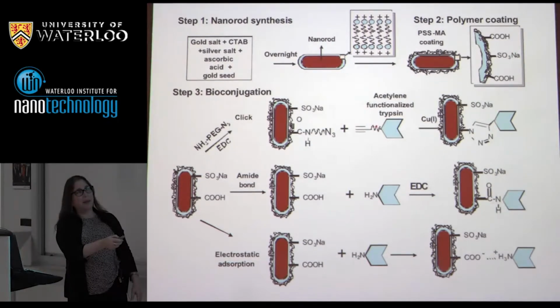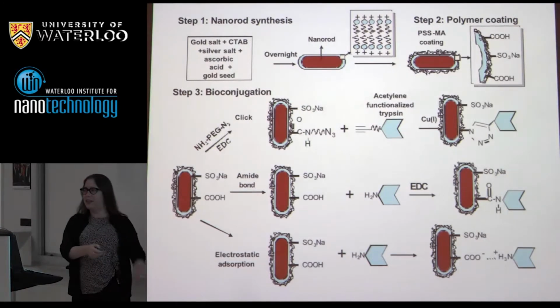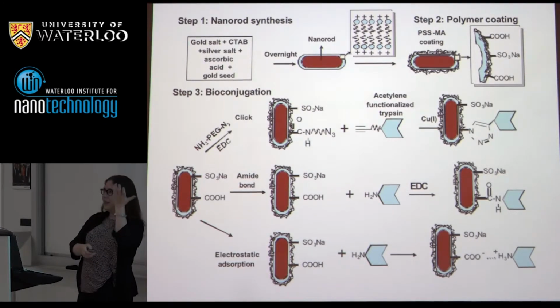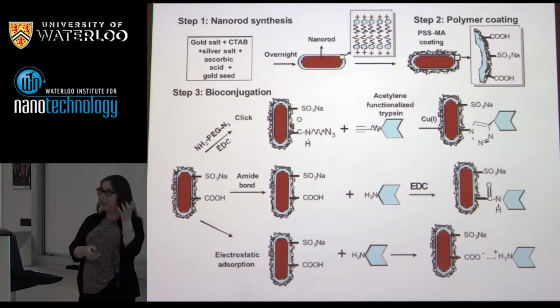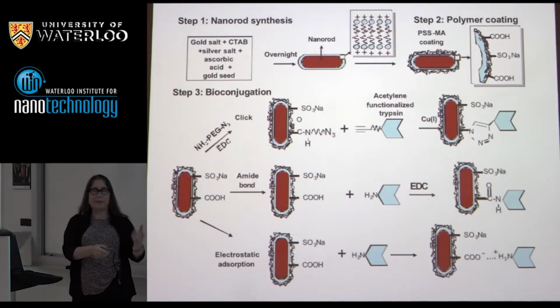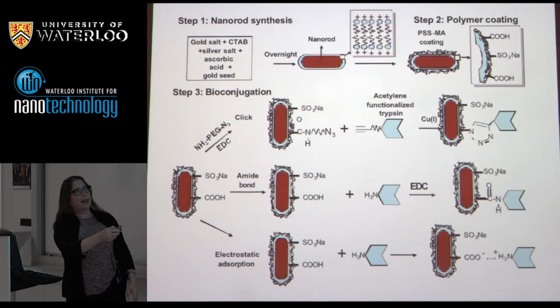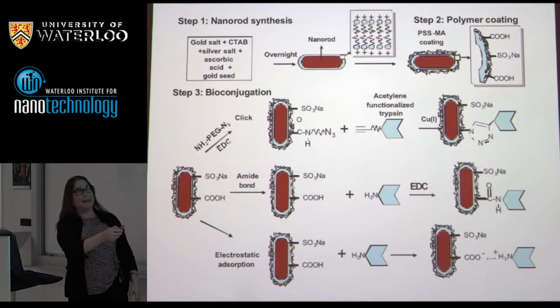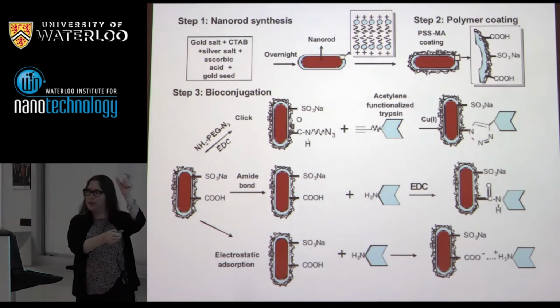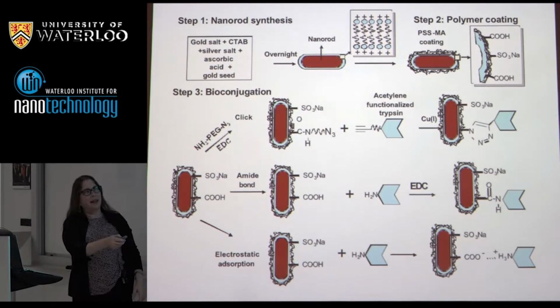So here you're going to make amide bonds between the 7 or 11 amines on the surface of trypsin with pentynoic acid. So then you have triple bonds facing the solvent, carbon-carbon triple bonds. That doesn't affect the protein activity at all when you do that. And then we're going to come in here and put on some azide, and you can buy this thing. So this is an amine PEG azide. So this is just a little PEG unit, 3 units long. Okay, and then we put it on.